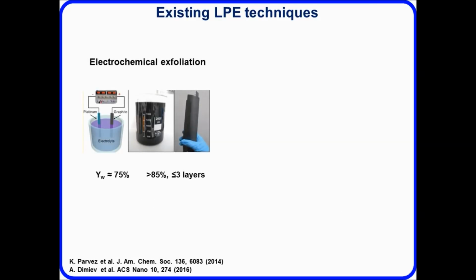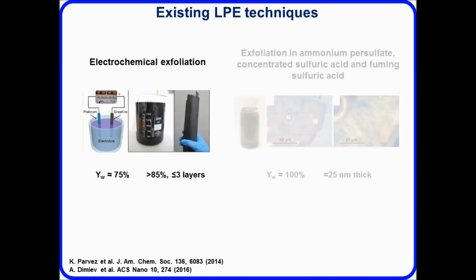You can do some electrochemical exfoliation. Using graphite as an electrode, you can apply a voltage. Essentially, that charges the graphene layers and causes them to repel each other, and they start to dissolve into your electrolyte. You can have quite a high yield process with very good quality graphene. However, you typically end up with a lot of other inorganic materials and inorganic salts as part of your electrolyte, which you need to wash away afterwards to purify your material.